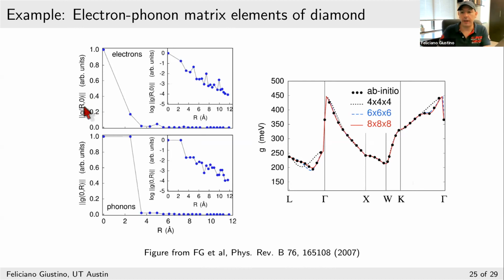So capital R gives the distance between one of the Wannier functions and the dipole and the first Wannier function. We can say that this is localized when you discover that your matrix element becomes orders of magnitude smaller when you move a few unit cells away. Ultimately, as Nicola Marzari said yesterday, one should always converge calculations with respect to this truncation in practice.